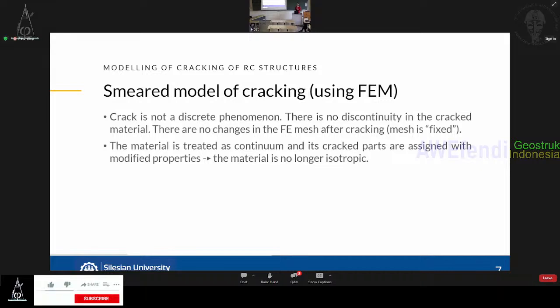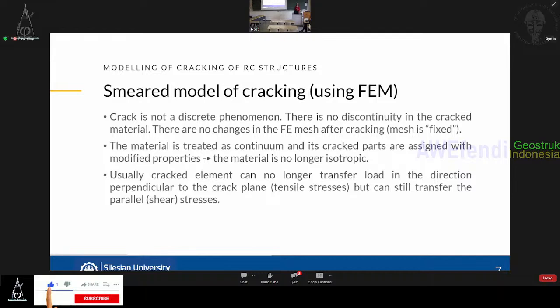And how do we approach this problem? In the smeared model, we treat the material as continuum, so it means there is no discontinuity. However, the parts of the material in which we reach the tensile capacity, so where we expect the crack to appear, are assigned some modified properties. So the material in these particular places in which the crack is expected is no longer isotropic, and usually such a cracked element is divided into, let's say, a healthy part and a damaged part.